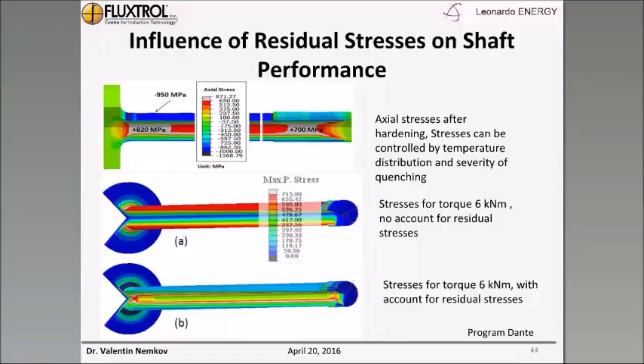Here we have axial stresses after hardening. And stresses could be controlled by temperature distribution and severity of quenching. You can see from simulation that the surface area, the hardened zone, has very strong compressive stresses, which is very favorable. At the same time, inside we have stronger tensile stresses, with especially big values in this zone and this zone. And we can predict that in some cases we can have internal cracks here. And in order to avoid that, we can change, for example, severity of quenching and avoid the danger of cracking here. So there are big opportunities for quality.